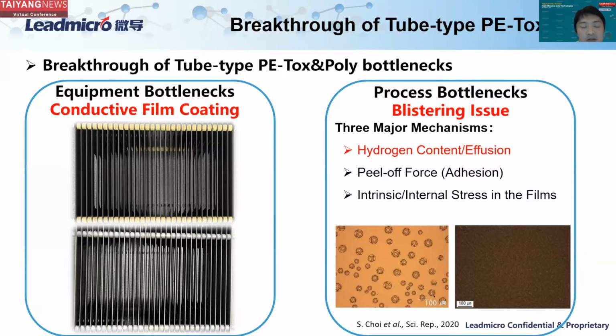Why is this critical? Use the graphite boat as an example. You can look at the top image. When we have two neighboring graphite plates, we have ceramic insulators to prevent conduction, because we are inputting AC current inside. If you are depositing insulating films, it's no problem. The ceramic will continue insulating.